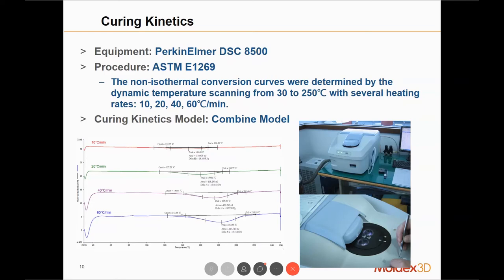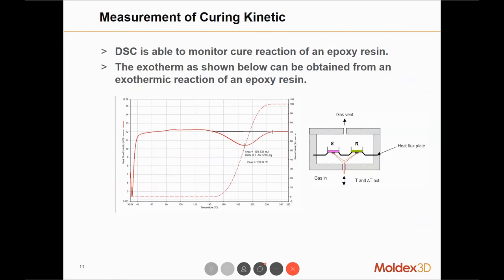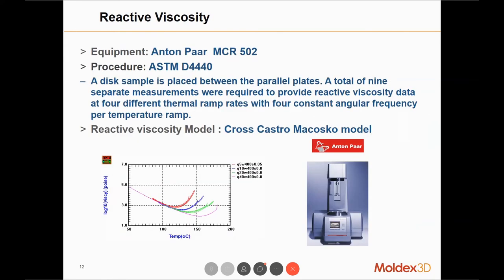So now that we know the curing kinetics, the next important thing is the viscosity, the reactive viscosity. We can use the MCR 502 under the procedure ASTM D4440. We will test the polymer with nine separate measurements, and pretty similar to curing kinetics, we will run the measurement at four different heating rates, four different thermal ramp rates, under a certain constant angular frequency.